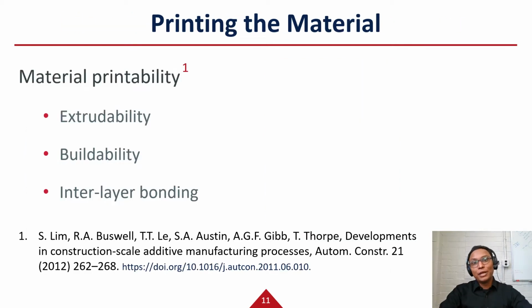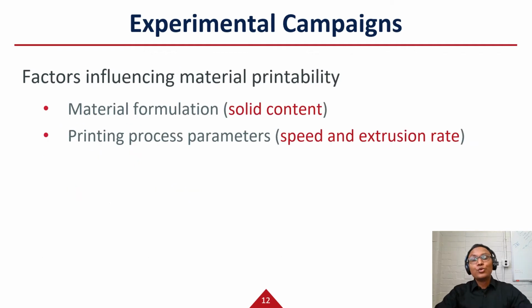Well, we have the material in hand, but to make it printable, we must ensure these 3 properties. First, the material needs to be extrudable and the deposition should be consistent. Second, it must retain its shape after printing. And finally, there should be interlayer bonding between the consecutive layers. To the best of our knowledge, there is no systematic research on the printability of this material.